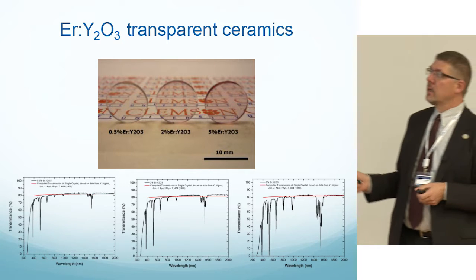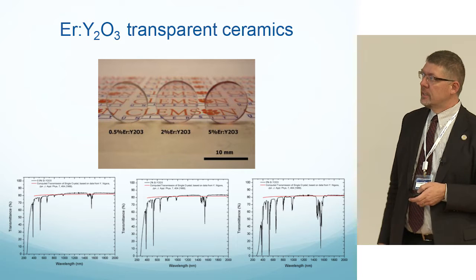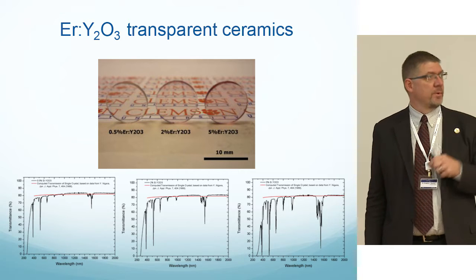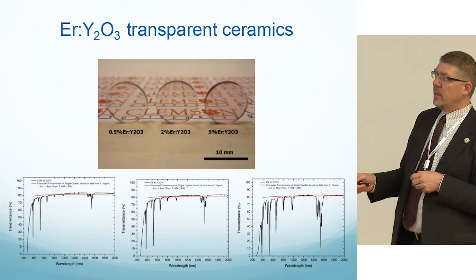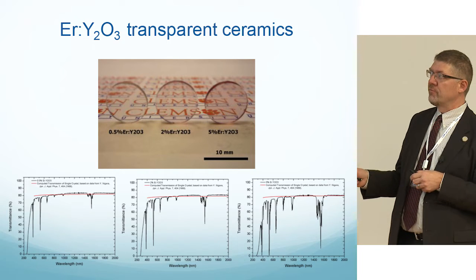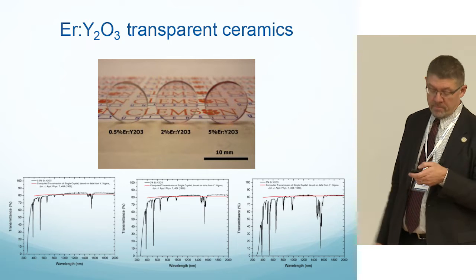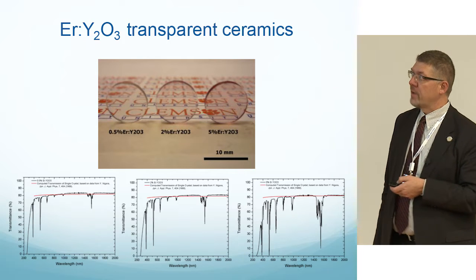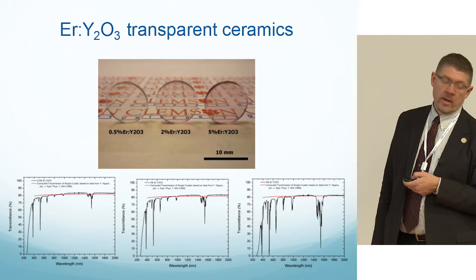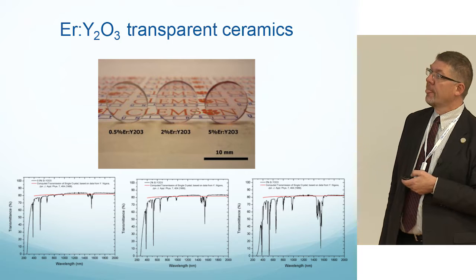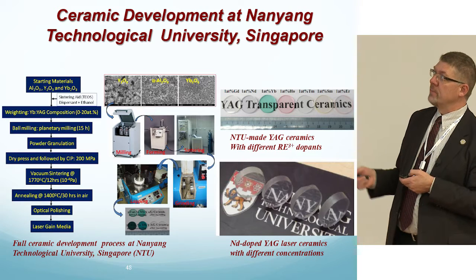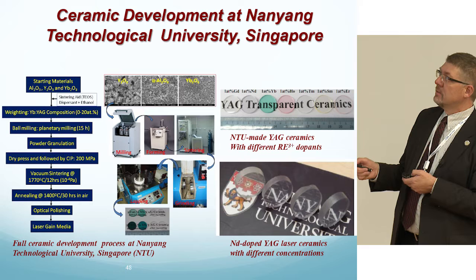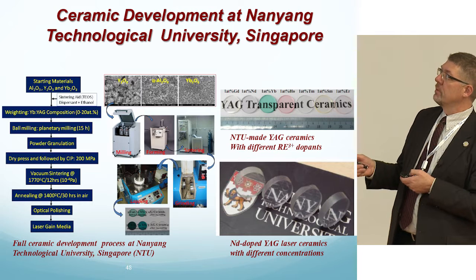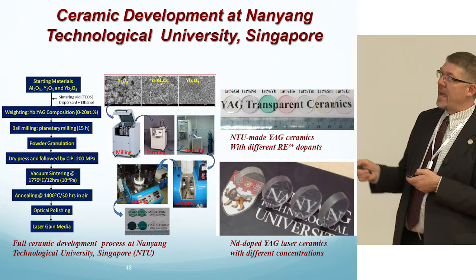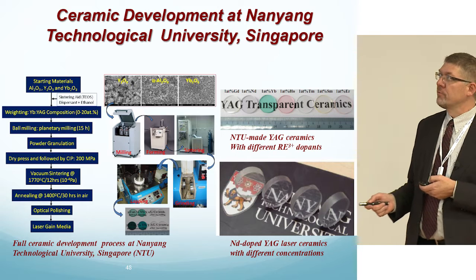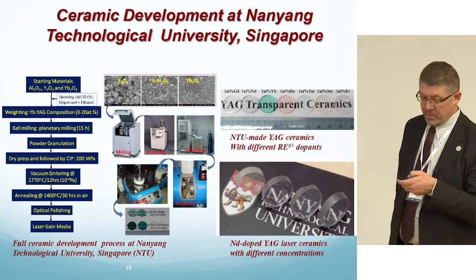I want to recognize some of the other groups that I showed previously. The group at Clemson's been doing erbium-doped yttria, trying to develop new thin disk materials for dental applications. The red lines here are the standard Fresnel losses, so they've been able to grow materials that match up well with the standard bulk index of refraction calculated from the Sellmeier equations. Dr. Zhang's group, now in Singapore, has done gadolinium, neodymium, ytterbium, holmium, thulium, samarium, and erbium, all in YAG. They've done a number of other materials too with a facility that very much mimics what's taking place with the Navy.